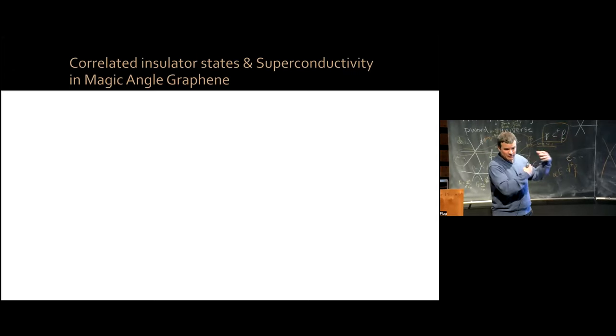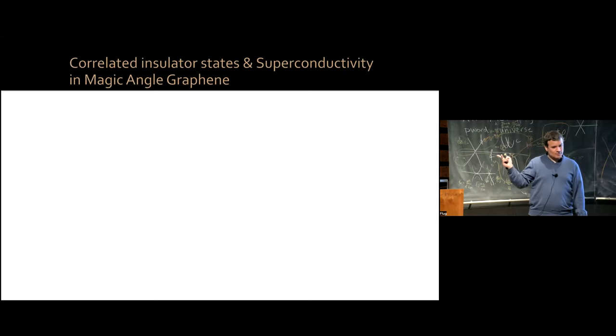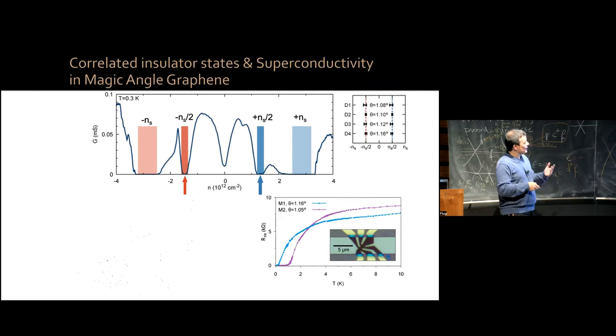well, first of all, was the fabrication itself of the devices, and then when you measure the electronic properties, the graphene is one of the best conductors in the world. It's not a superconductor. It's definitely not an insulator. What we did is we put graphene on top of graphene. You would think, you know, this is like the apple and the orange, right? You would think that graphene on top of graphene would look, taste, smell, you know, like graphene. It does not. So we could make a correlated insulator and we could make a superconductor.